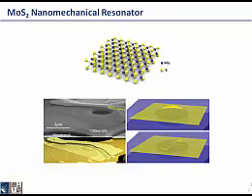It is an atomic layer material. It's a semiconductor. It's very thin. The single layer could be just 0.7 nanometers. And it's got a pretty good on-off ratio when you make it into electronic devices. And it's compatible with other two-dimensional, we call it 2D, nanoelectronics.